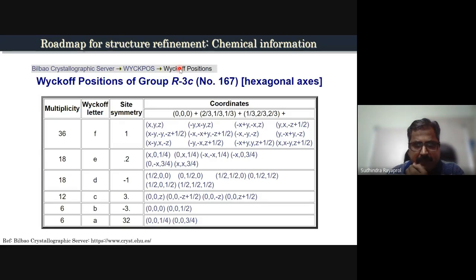Now coming back to the space group, there is something called the Bilbao Crystallographic Server. You can go to this website, ehu.es, and look for the Wyckoff positions. You have to give the space group number, or you can identify the R3c space group, which we have confirmed from our Le Bail fit. If you look into the Wyckoff positions, it gives you the set of positions or coordinates at which the atoms can be placed.